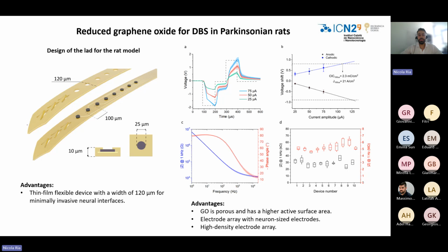The electrochemical characterization of this electrode shows that for typical stimulation protocol as the one used for deep brain stimulation, so biphasic current pulses of 100 microseconds at increasing current amplitude, we can inject up to 2.3 millicoulomb per centimeter square, so a current density of 21 amps per centimeter square, which is a very high value compared to the standard platinum electrodes that are available in the clinics.